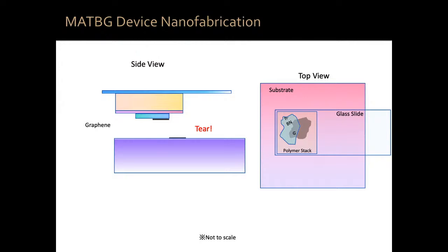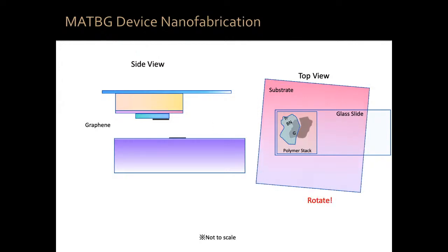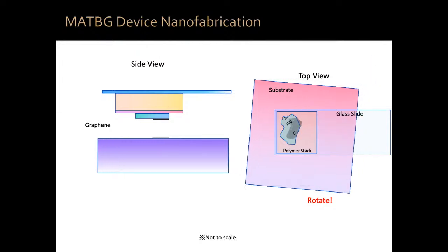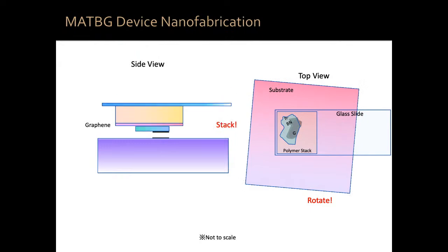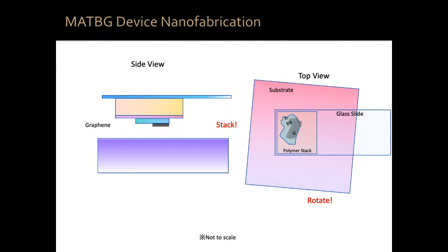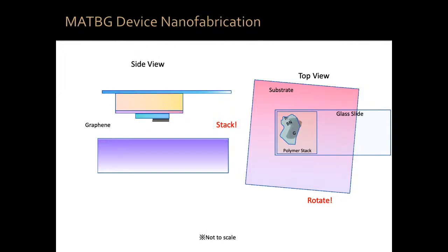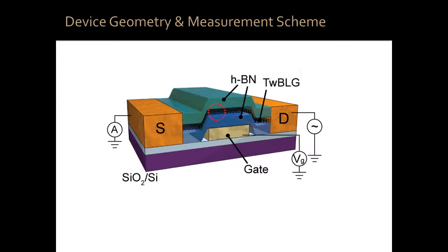Now, we can rotate the substrate or the slide by any angle that we want, in particular 1.1 degrees, why not? And then we shift it and stack it on top. In this process, we pick up the second layer, and then we continue doing our nanofabrication process. And amazingly, this produces a long-range ordered pattern of these two graphene sheets at that angle, which creates a periodic Moire pattern. Once you've done this, the rest of the fabrication process is very standard. Many groups around the world can do that. You have this twisted bilayer graphene at any angle that you want.